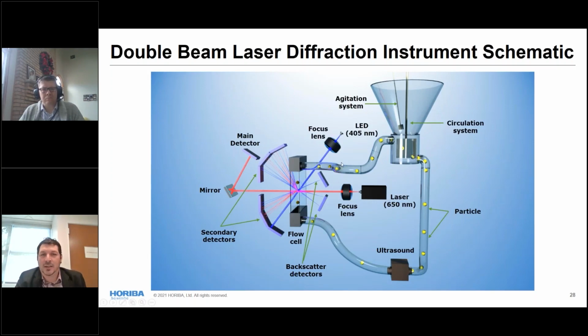I'm not sure if this clarified your question, which was what difference we measured with one laser versus the other. The difference is not in the most appropriate size, because the instrument picks it automatically. It measures with both and makes a convolution of all the results. So you don't need to worry about setting up your analyzer to read one light source after the other, even though we have this option. The reason we have the option to shut down one of the light sources is when you work with a pigment or a sample that has very high absorption of one of the wavelengths. That is the only case in which we would turn one of the light sources off.